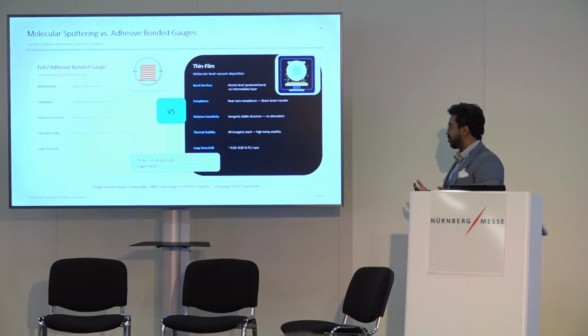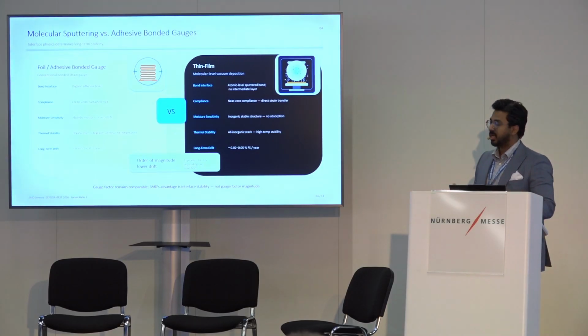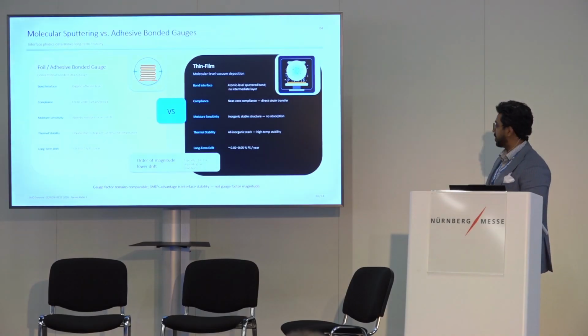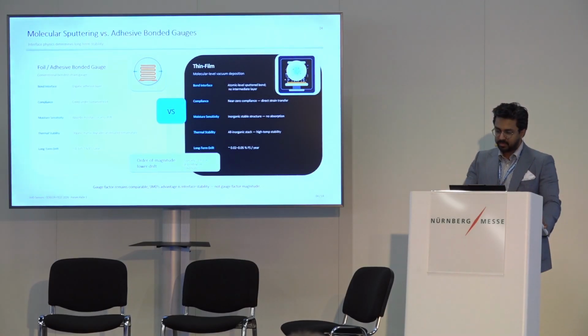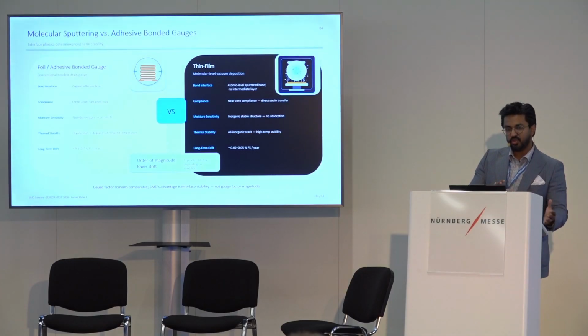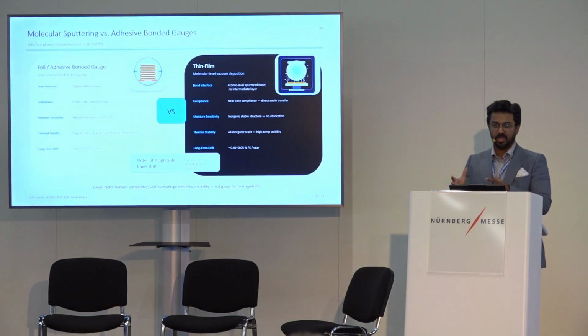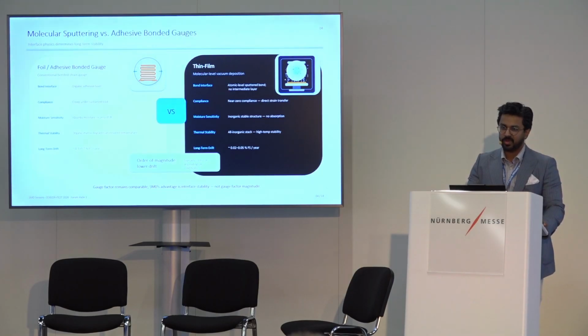But when we do thin film, we look at the bond interface, and it's an atomic layer bonding. It could be sputtered, chemically deposited, or additively done as well. That skips the glue entirely. The sensing film is deposited directly onto the substrate at the atomic level, with no intermediate layer, no creep, no moisture path, and just an all inorganic stack. The number on the right tells the story: depending on conditions, if you choose between adhesive bonded and thin film gauges, you'll see a 10 to 20 times improvement, but cost comes into account here.